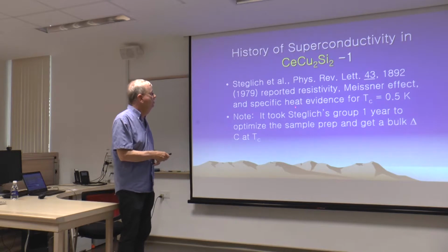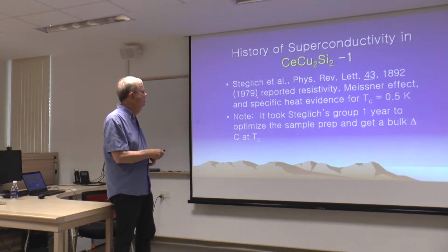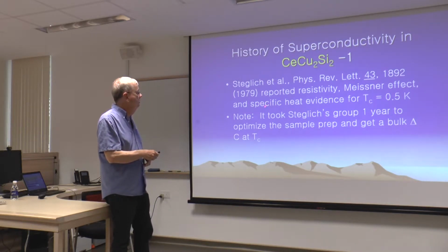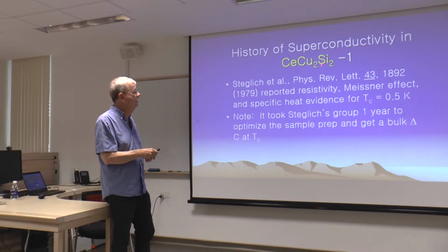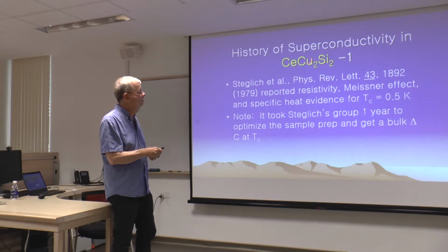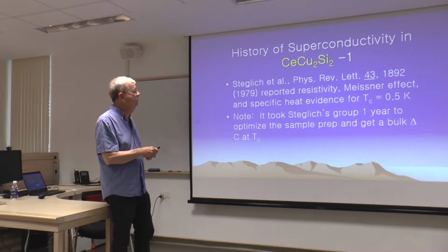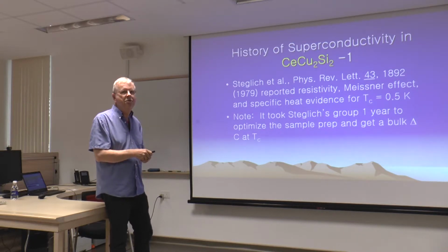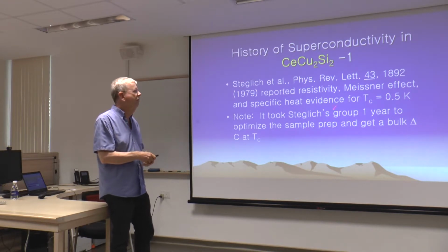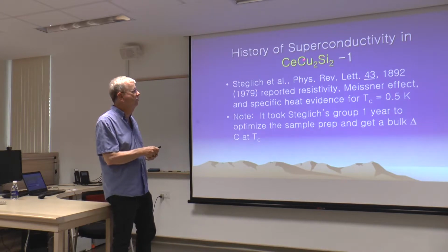Okay. So Steglich had trouble making this material into a bulk superconductor, and we all know the trick today. If you want to make this material have a bulk TC, you have to have extra copper. So if you make cerium copper 2.2 silicon 2, you'll get a nice transition. If you make copper 2, you won't. You'll be in the wrong part of the phase diagram because there's anti-ferromagnetism running around in this phase diagram.